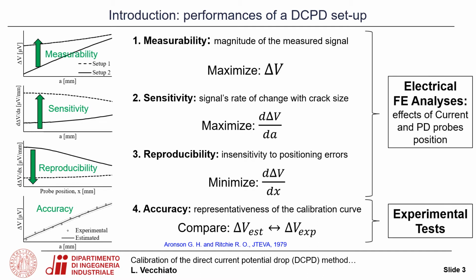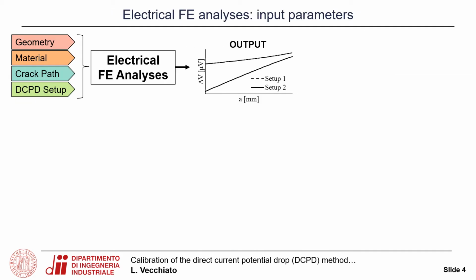In this work, we performed the electrical finite element analysis to check the effects of the current and potential drop probes in terms of measurability, sensitivity, and reproducibility, while lastly, experimental tests have been performed for studying the accuracy. So, starting from the electrical finite element analysis, it requires as input the specimen geometry, the material properties, the crack path, and information on the DCPD setup. And it gives us, as an output, the different calibration curves for different DCPD setups to be evaluated in terms of measurability, sensitivity, and reproducibility.